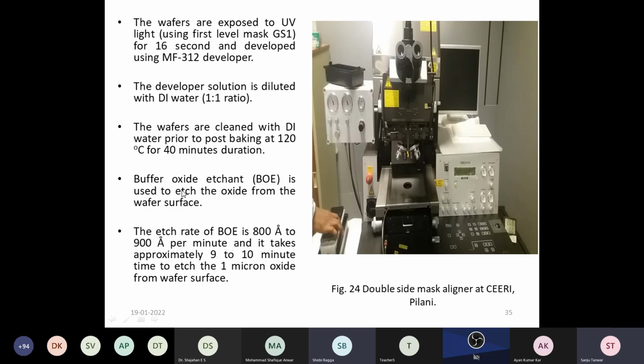Now what we have to do is remove the oxide from that part, because only then can we reach the silicon depth. Buffer oxide etchant is used to etch the oxide from the wafer surface, and the etch rate of BOE is 800 to 900 angstrom per minute, and it takes approximately 9 to 10 minutes to etch the 1 micron oxide from the surface, because we have kept the thickness of the oxide as 1 micron. So first we have etched the silicon dioxide completely, but this is going to work like a passivation layer.